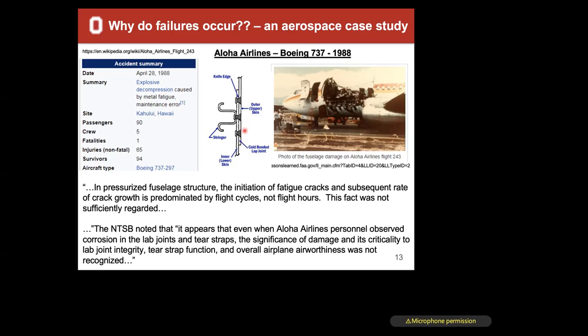And what the cause here is that when next time you fly, look on the aircraft and you'll see these bays of the fuselage. And what they actually do is they put them together, and this is called a lap joint, where the fuselage section of one part overlaps with the other, and then they rivet it together to hold the whole plane together. And in there, you can leak in electrolyte, leak in environment, salt water, whatever, right? So salt spray that's coming up. Even the environment here in Ohio is enough to get an electrolyte in there, right? So you get this electrolyte in between your lap joints, and corrosion can occur.